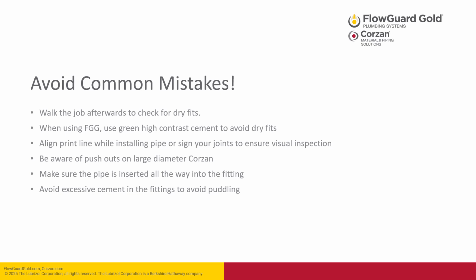Make sure the pipe is inserted all the way into the fitting. And avoid excessive cement in the fittings to avoid puddling. It can be difficult to put too much cement on the pipe, but it can be comparatively easy to put too much cement in the fitting. Always make sure that there's not excessive cement inside the fitting socket.